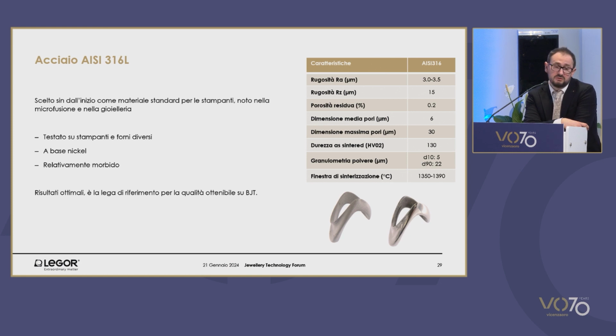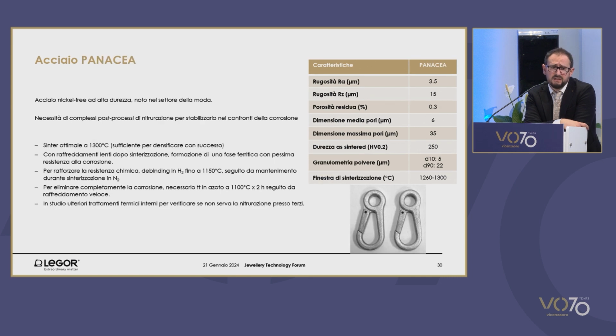And this is the list of the materials that we have treated. The first one was steel, AISI 316, with excellent results. We believe that this now is mature, and it has a pretty wide sintering window. Powder granulometry, as initially suggested by the supplier. Well, this steel has the characteristics that are desired. The presence of nickel as such can be a limiting factor in some markets, but the softness and the mechanical resistance, which is not all that high, could actually play a role.